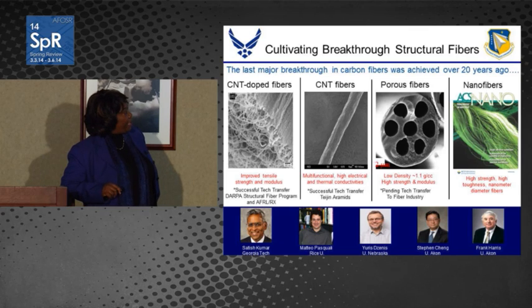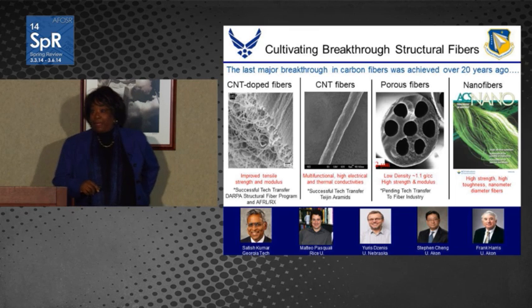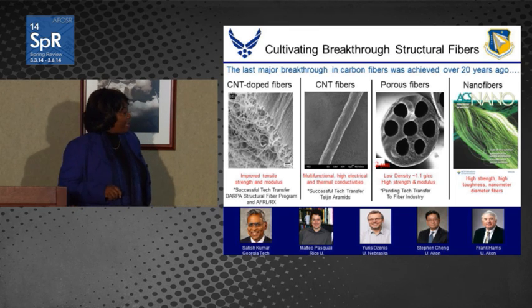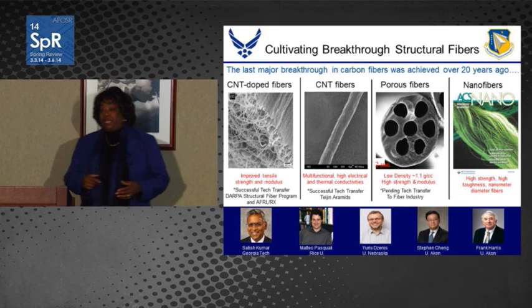And then lastly, I want to highlight work that's relatively new. It's been underway for about a year or so now, and that's work on developing nanofibers using electrospinning. And this is an example where one of the interdisciplinary teams came to me with the idea of making a wholly polymeric composite structure. It's a pretty far out idea that needed engineering capability for electrospinning fibers, but it also needed new innovations in terms of synthesis, making new polyimide-based resins that you could spin and make the fibers out of and then consolidate into composites.